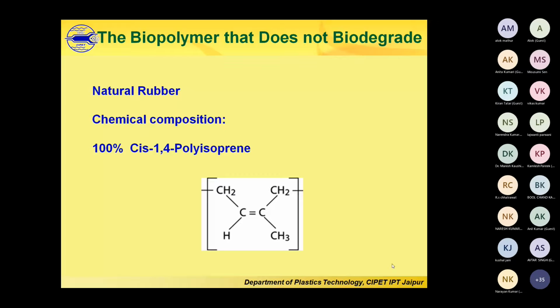So how do you get back the original properties? Well and good, you have made a shape from the rubber now, but you need the strength again. So the chemical invented for this is sulfur. Charles Goodyear invented this sulfur. When you add sulfur into that soft rubber compound and heat it to around 160 degrees centigrade,